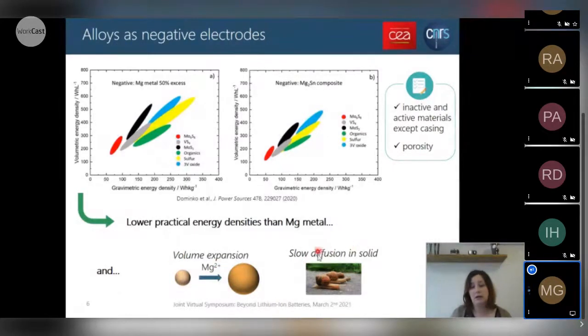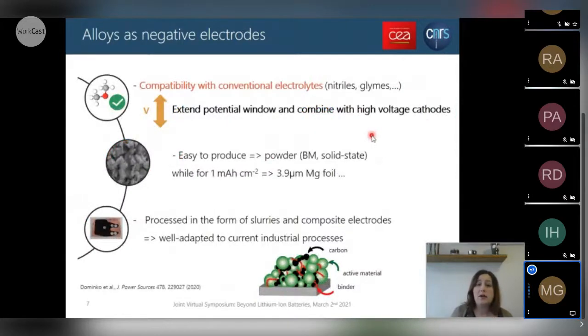And the second challenge is, as I mentioned before, the slow diffusion of magnesium ions in the solid in general. Yet there are many advantages of this alloy negative electrode that in fact counterbalance these drawbacks. The main one is that these alloy materials are compatible with conventional electrolytes, such as nitrile and glymes. They do not form any blocking passivation layer with this electrolyte. So they offer a way to extend the potential window of magnesium batteries and thus to combine them with